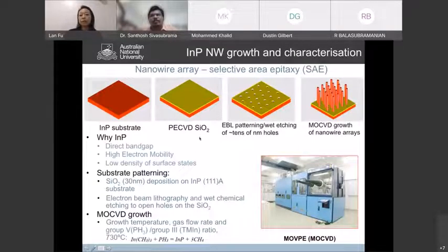So let's look at a little bit of detail of how we do that. If you have a substrate such as gallium arsenide, indium phosphide, or silicon, we deposit a thin layer of silicon dioxide on top of it using the PECVD technique. Then using electron beam lithography, combined with wet chemical etching or reactive ion etching, we can open little holes in this silicon dioxide. And then we put it into the MOCVD reactor, the metal organic chemical vapor deposition system, which is a very industrialized reactor for epitaxial growth. That's the system used to grow a lot of the lasers and LEDs that are used every day. So we put it into this system and we tune the growth conditions.